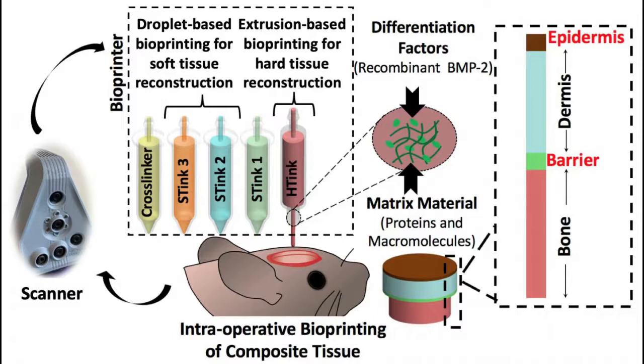They used collagen and fibrinogen in alternating layers with cross-linking and growth-enhancing compounds. Each layer of skin, including the epidermis and dermis, differs, so the bioprinted soft tissue layers differed in composition. Experiments repairing 6 mm holes in full thickness skin proved successful.